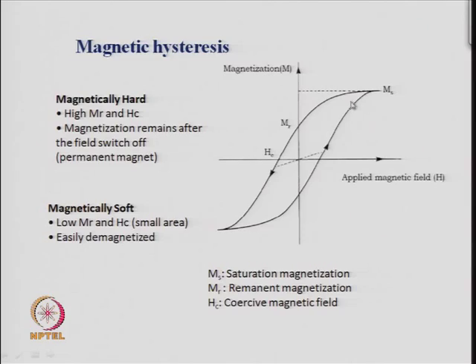And the area under the loop tells you about the material, about how hard is the magnet or how soft is the magnet. So, something which we say is magnetically hard. What does it mean, something to be magnetically hard? Means it is difficult to magnetize that sample. That means you have to give a very high magnetic field to reach saturation magnetization.